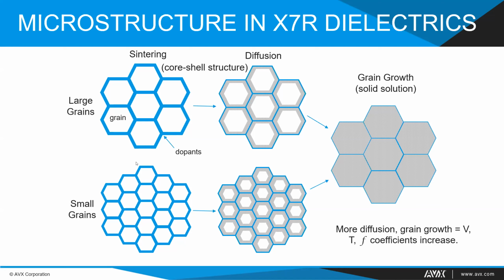Now, as we begin to start consolidating and firing this material, we can start with a fairly tight region in the grain boundaries of a range or a spatial distribution of the dopant materials. But as we heat the material up, that material can diffuse and create a much wider grain boundary or core or shell region, leaving less and less of the core behind. And if we let that diffusion process continue, we can actually diffuse those elements right through the grain. And at some point, we'll actually lose control of the grain size, because the grain boundary dopants that were out there that were meant to control grain size all of a sudden are now incorporating the grain, and grains can grow from that position. And so all of a sudden, that causes an increase in grain size, which makes us lose control of all the temperature and voltage coefficients that we were looking for.